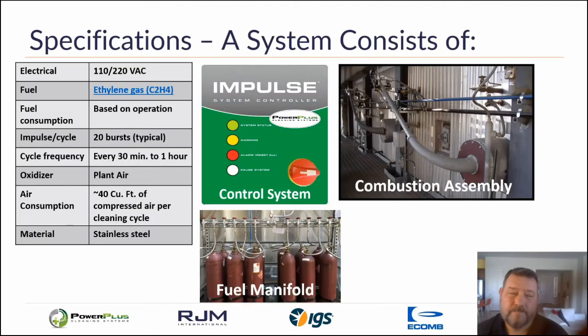A typical system consists of a control system that monitors the impulses and puts the system into a fault within 1.5 or 2 seconds if it notices that there is something that is not operating correctly. It doesn't matter if it's a lack of gas or a bad igniter. It doesn't allow uncombusted gas to be injected into the boiler. It also tracks the pressure in the flow in the supply line leading up to the unit, so if there is any small leak, it will also put it into a fault. There are many safety factors built into the control system to prevent any problem from happening.